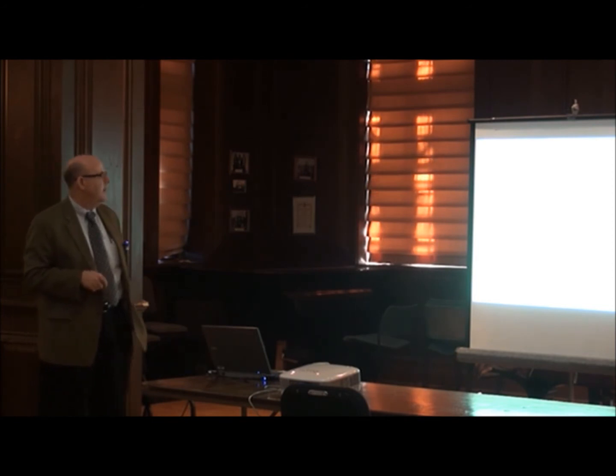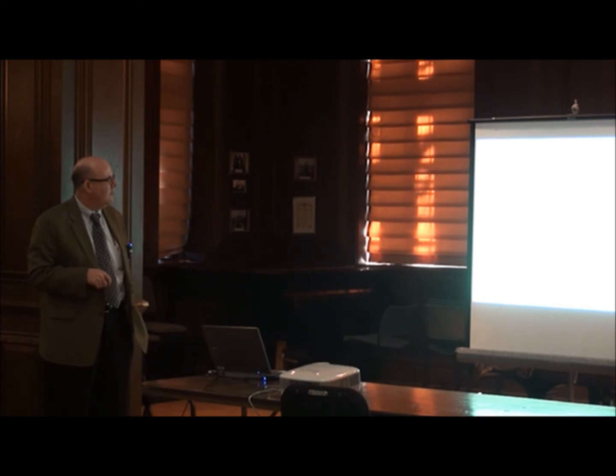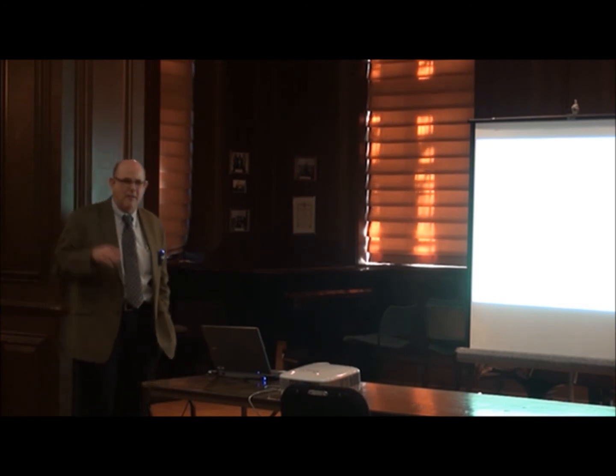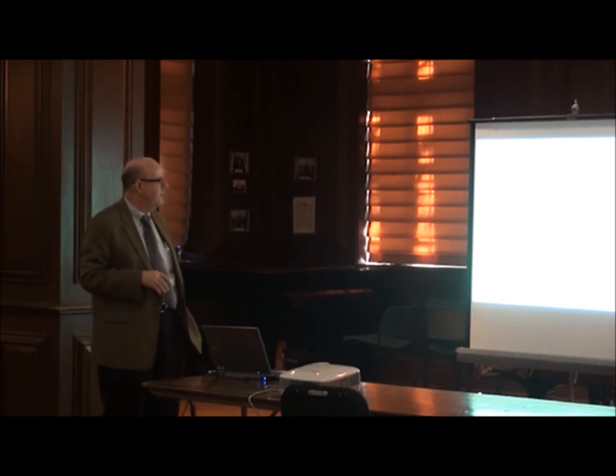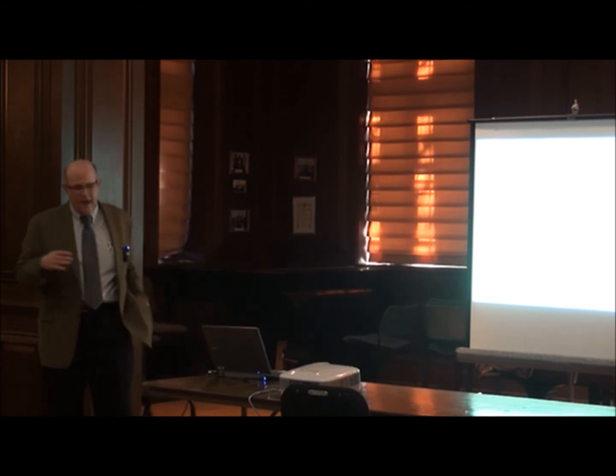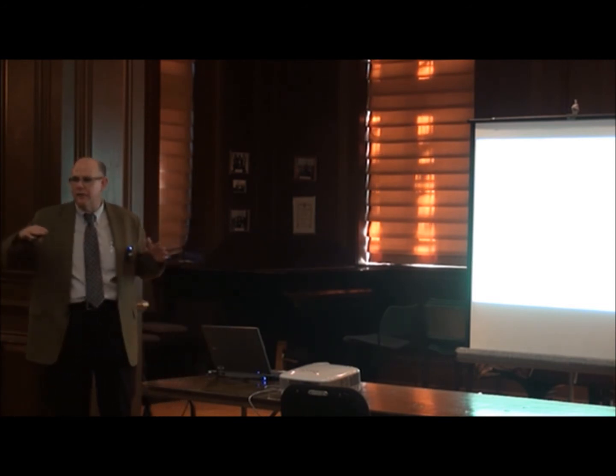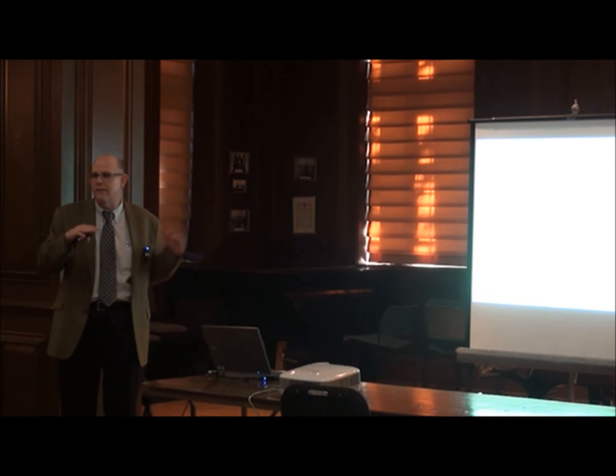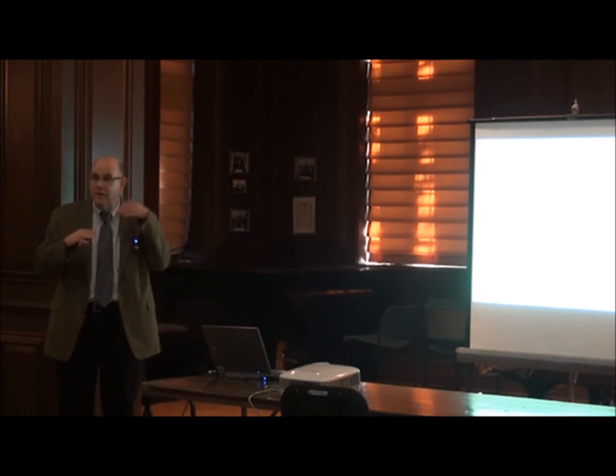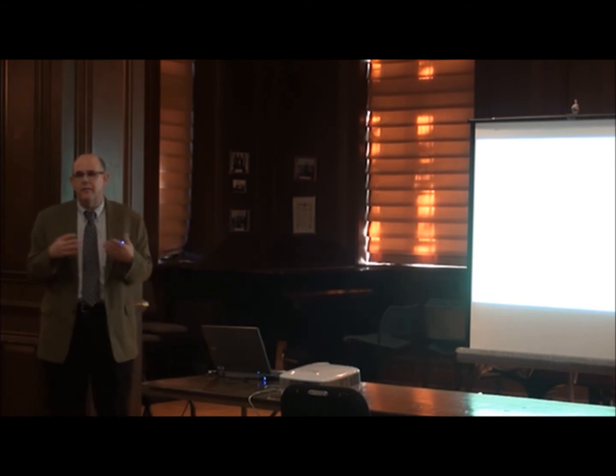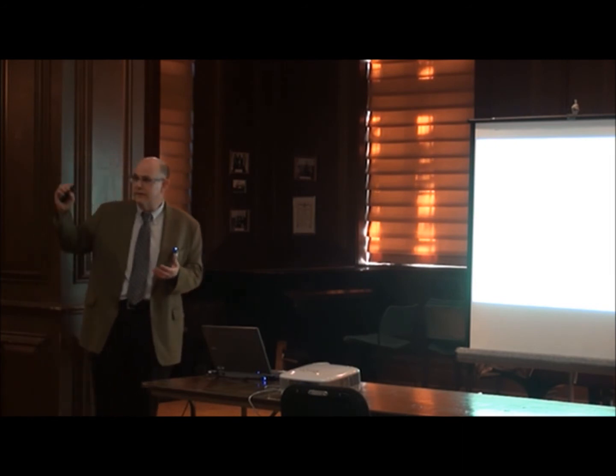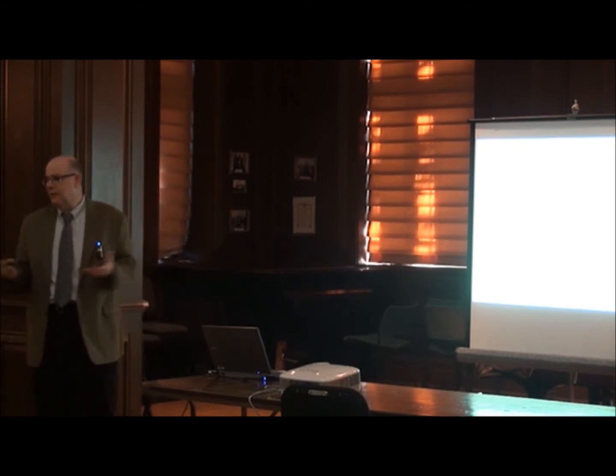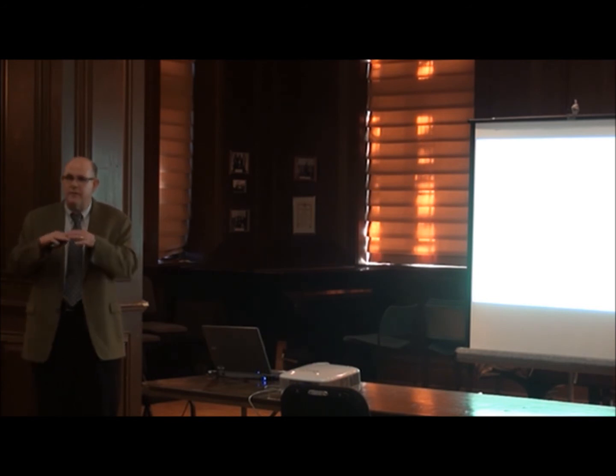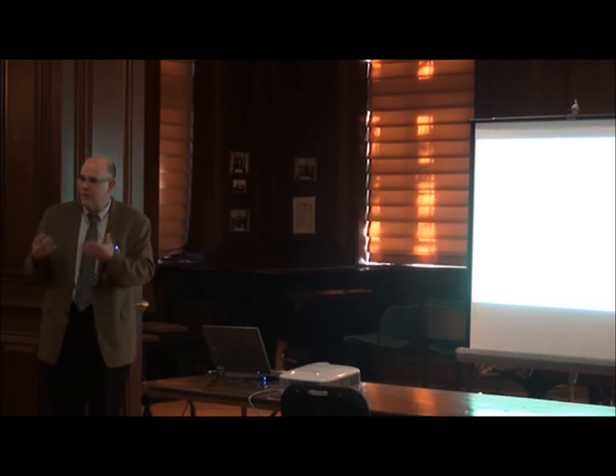Here's basically a quick little summary from the work from Christensen in the 70s. You just kind of look through this table. It shows you what you might think might happen from a physical point of view. Just as a typical example, if I have a nice clean bearing system and then all of a sudden introduce transverse roughness to the sliding interface, that's going to prevent fluid flow. And if I'm going to prevent fluid flow, just like putting a small gap in there, I'm going to have to build up a higher pressure to balance that system. So as a result, with transverse roughness, I actually can support a little more of a load.